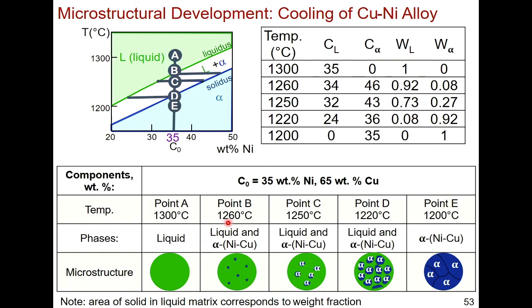And then at 1260 C, you start to get some nucleation, right? That's a little bit below the liquidus line. This dot looks like it's a little bit above the liquidus line, but it's below the liquidus line. So then you get some solidification here. These are the blue dots that you see. So here you start to get some solidified alpha that comes out of the liquid solution. And then at point C, what we just talked about, the amount of solid you have increases. So the weight fraction of solid increases. And then you drop the temperature some more. You're slightly above the solidus line, so you still have some liquid green. And now the amount of alpha solid that you have has grown even more so. And then eventually, when you're in E, you have an entirely solid system. So it's all alpha, all blue.